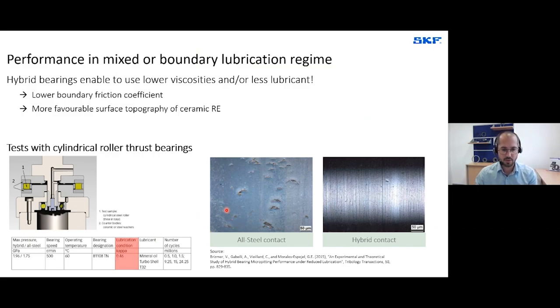And what can be seen immediately is that the all-steel contact really suffers from those poor lubrication conditions. There is significant wear visible, and you can also see those micro pits on the ring surfaces in an all-steel contact. While the hybrid contact actually still looks very good. There is no sign of micro pitting, no sign of early failure due to low lubrication film thickness. And this makes it the perfect choice if you want to really reduce friction, go down in lubricant viscosity, go down in oil volumes, and select hybrid bearings in your machine.